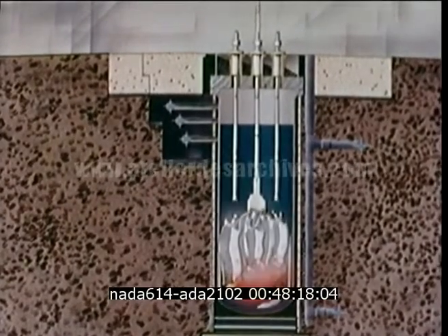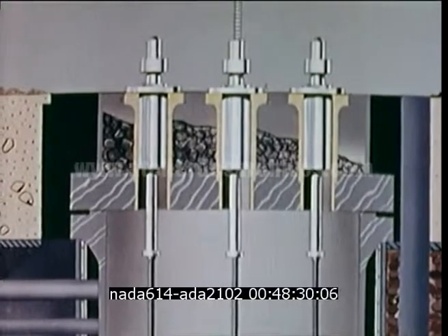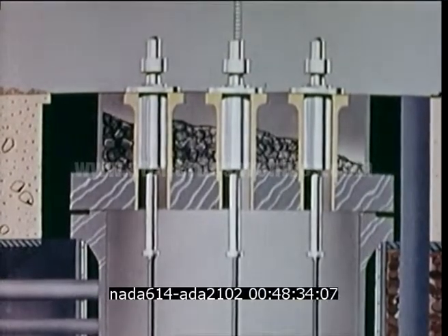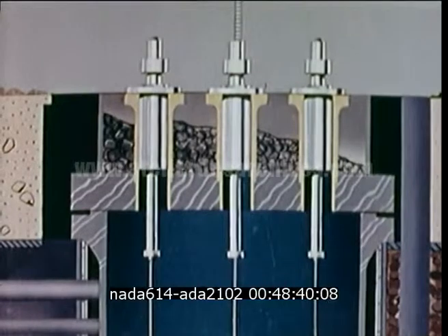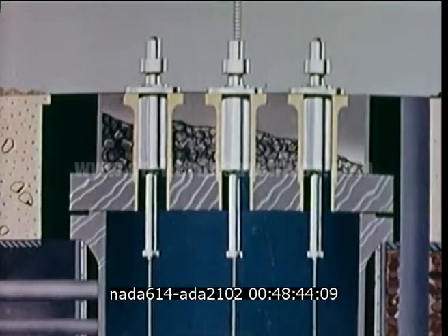The central blade was seized by the shrouds surrounding it, and the two became an integral unit. At this time of seizure, the central blade was withdrawn about 20 inches. The steam being generated pushed upon the water that was above the level of the core, forcing the slug of water upward from the core zone. It was stopped by the vessel head, with a resultant water hammer causing peak pressures of about 10,000 psi.